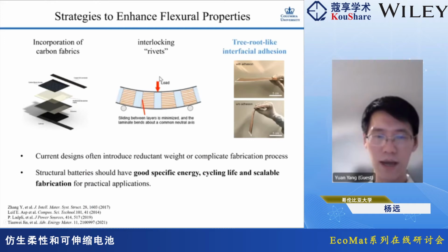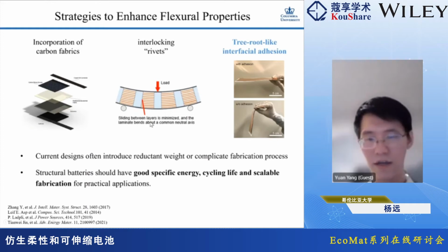Another strategy is to have some rivets inside. The rivets connect the top and bottom of the packaging, basically fixing the top and bottom of the packages, so that when you bend it, there will be almost no sliding between different layers, and the mechanical stress can be enhanced. But this process is not easy to fabricate; it has a very complicated fabrication process.